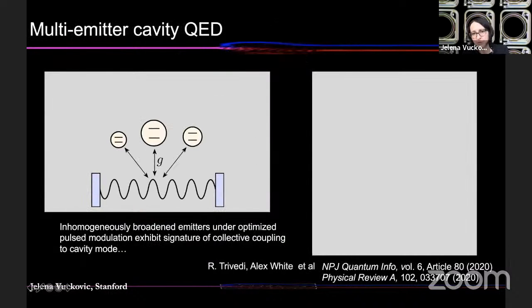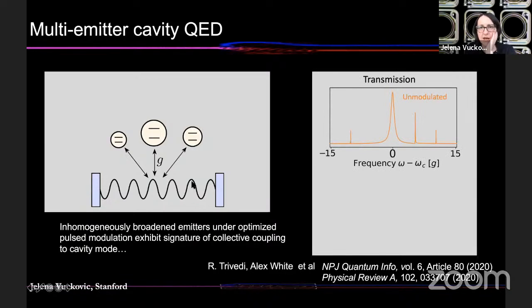Then the other problem we looked into is the problem of multi-emitter cavity QED. And here also my student Alex worked on this problem with Raul. What is multi-emitter cavity QED? Again, I told you that the state of the art for cavity QED with silicon vacancies in diamond is coupling of two atoms to the same cavity at Harvard, but people were fortunate that they could actually tune these two detuned emitters onto the cavity resonance by an external magnetic field. So we were interested in whether, if you have 3 or more atoms and they're different from each other, detuned from each other, can you couple them to the same cavity by doing some sort of optimized drive on them?